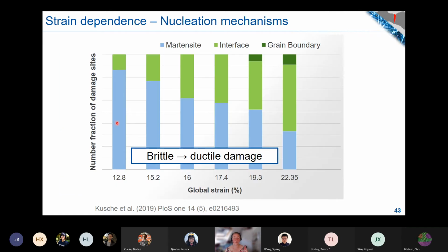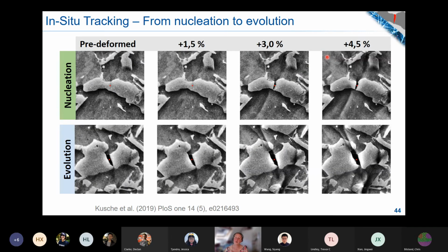So if you want to of course avoid damage altogether, you then have to look for the martensite originating at low strain, or you might have to engineer the interfaces later to maybe avoid growth as well. We can also use this to help us with in situ experiments, because if we have lots of damage sites that we track for different deformation states and do this in situ in the microscope, then we can go for rare events like the nucleation stage and see whether they've been there in previous images.